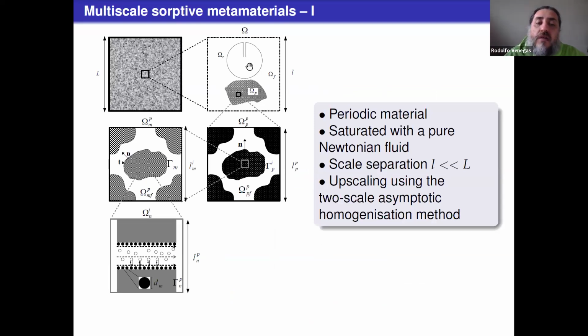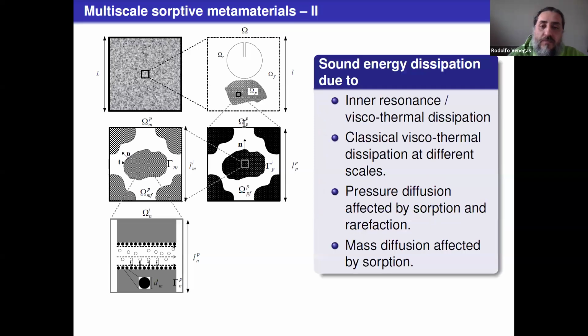So we have an array of resonators, and within the representative elementary volume, we have inclusions of nanoporous or multiscale nanoporous materials. So the idea was to get the best of both worlds: the best of metamaterials, where we can exploit resonances, and the best of the multiscale sorptive materials, where we have very strong sound energy dissipation at low frequencies. So we will apply homogenization to this problem, and the sound energy dissipation will be due to inner resonances, viscothermal dissipation, classical dissipation, and viscothermal dissipation at different scales, pressure diffusion, mass diffusion, etc.